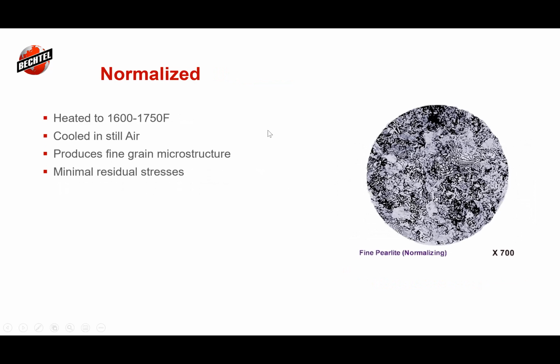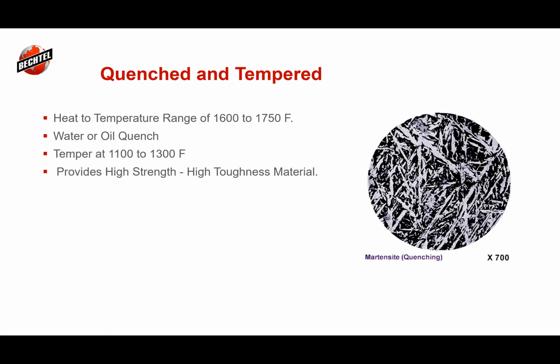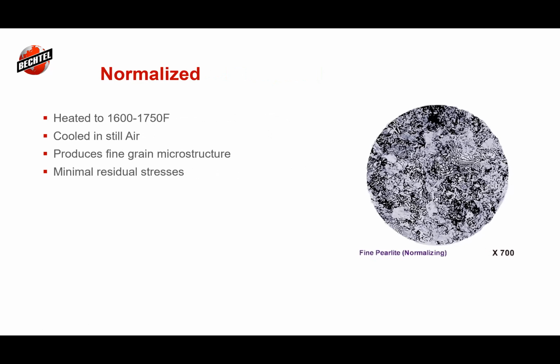Normalized materials, I think we're going to move on. Normalized and quench and tempered. I think I brought it up. The A36 is an as-rolled material; sometimes you can get an A36 modified, and sometimes you get materials that are normalized. So the A36 is as-rolled. It comes off the rolling mill and lays out to cool. Some of the materials, particularly if you work with any of the 516-70 materials, 537 Class 1s, those are plate materials, and a lot of those will be normalized. They take it back up into that austenitizing range, let it austenitize, and then let it slowly cool down.